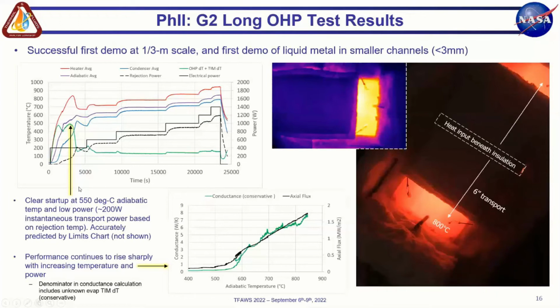We have clear, repeatable, and predictable startup at about 550 degrees adiabatic temperature, and actually quite low power. Onset of nucleate boiling here, we can see the spatial gradient in the part fall off a cliff from 500C down to 100 or so, and then again steadily improving performance with temperature and power. And that's plotted here in the lower plot, along with the axial flux on the secondary vertical axis. We're actually pushing here, coming up on 2 megawatts per meter square of the transport cross section, which is a number that's been of interest to some of our folks interested outside of NASA.